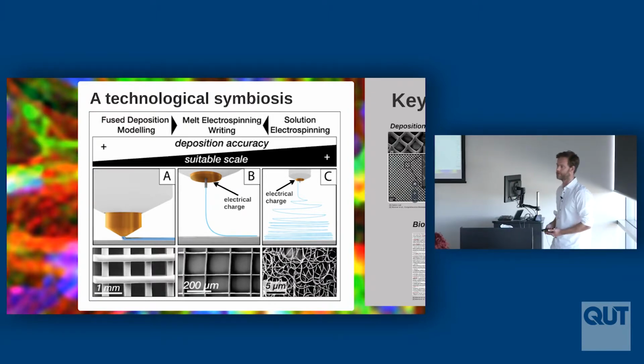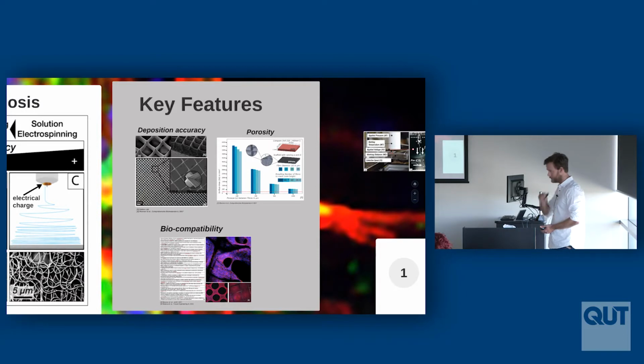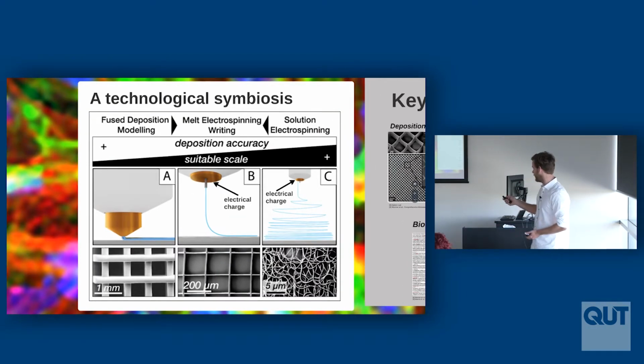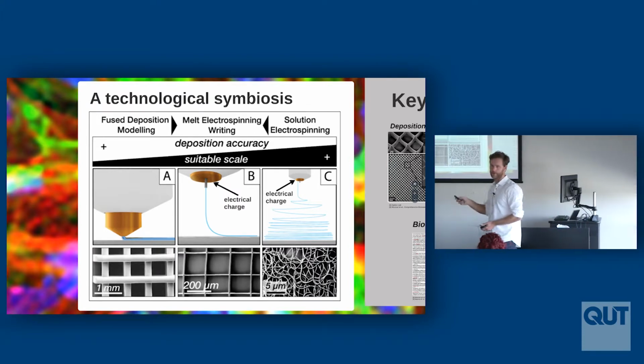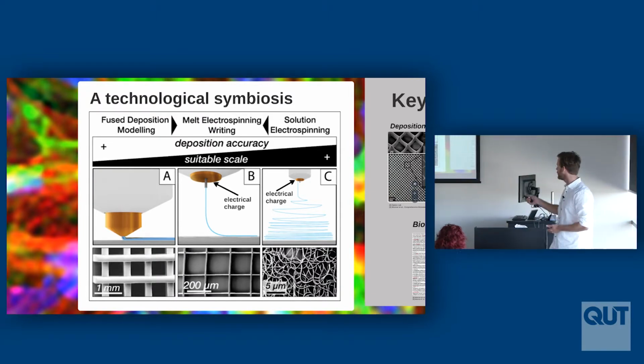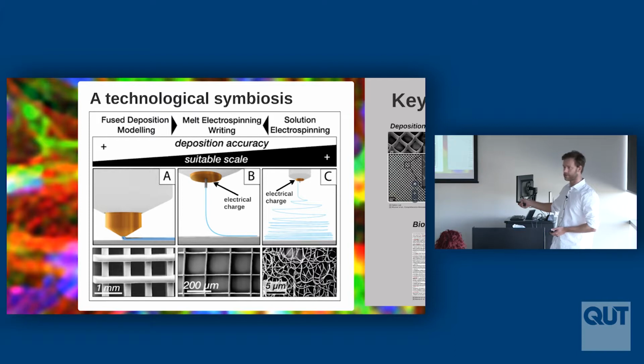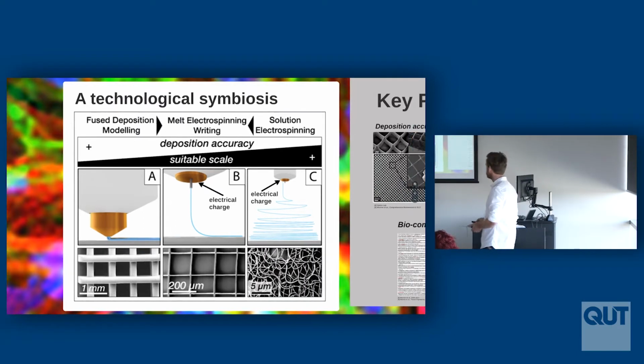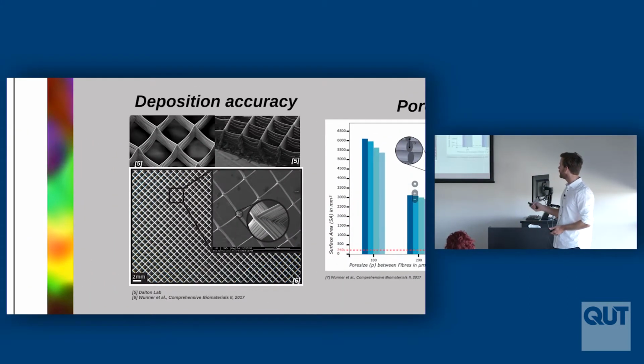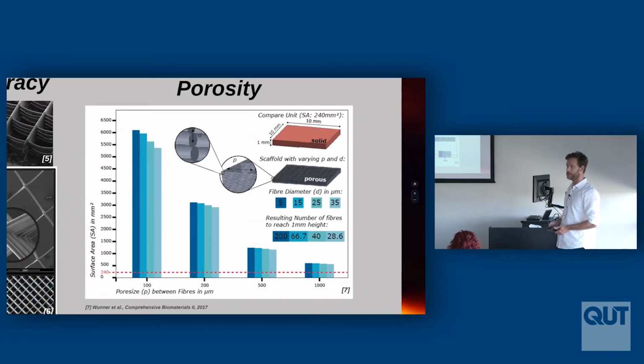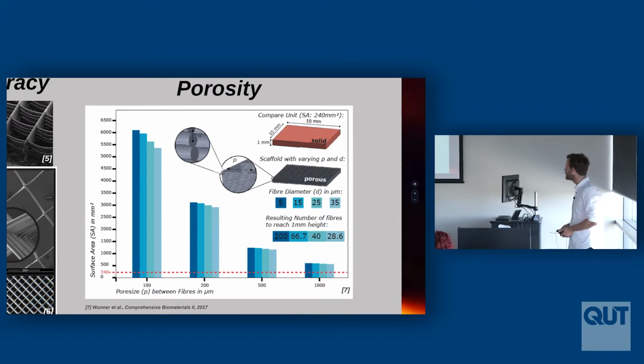Dietmar and his colleague Paul Dalton published a very important paper, which I don't show here, shame on me, in 2011, where they decreased the collector to needle distance, and substituted the polymer dissolved in a solution with just heating the polymer. So it had a better viscosity, a better molecular stability to catch the fiber in a direct writing way. At the end of the day, they started to be able to create 3D printed structures with morphologies in the lower micron scale. Again, the key features: we can now deposit really small fibers very accurately, and can create large, highly porous constructs, which are really important for the tissue engineering community.